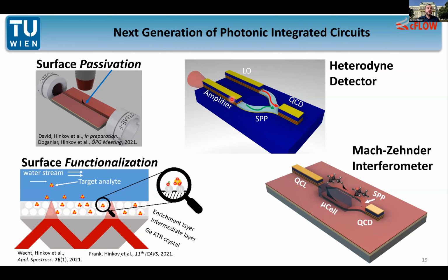And the same is true for the germanium, for example. So this worked very nicely. Even though it's sputtered, it has some roughness, but at this wavelength where we are, we didn't see any drawbacks. And actually, when we compared it to evaporation, which is known to have much less roughness, the sputtered one was equally good. So this is a fast process, and therefore, if you think of commercialization or industrial applications, this is something that is absolutely state of the art.